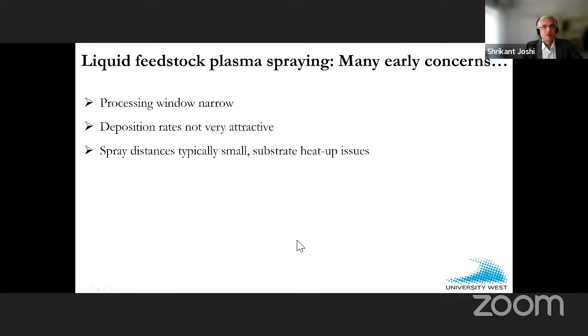Right. So when we first started work using liquid feedstock, there were several initial concerns. Some of these I've listed here. One was that the processing window was quite narrow. The deposition rates were pretty dismal, actually, and one struggled to put on a reasonably thick coating. I remember our first year or two of solution precursor plasma spray. We needed to spray coming in very close to the substrate, so there were substrate heat up issues. So if the jury was out then, most of them agreed that this was too far from being exciting on the thermal spray shop floor, right?